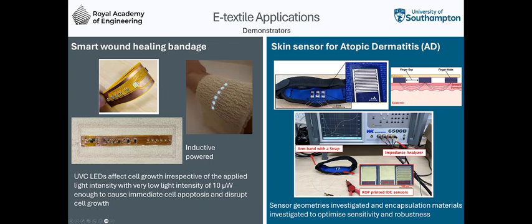Another example sensor here is an IDC electrode structure that's attached to an armband, and this is used to monitor atopic dermatitis, which is an itchy skin condition, quite unpleasant for people who suffer from it. These have been designed specifically such that the electric field is concentrated in the top surface of the skin, and it looks at the dielectric properties of the skin. If you've got a region with atopic dermatitis, then the dielectric properties are different. And you can use this sensor to see how bad the atopic dermatitis actually is. And it's obviously wearable. It's something the patient can use themselves. So we're developing this further with the local hospital.